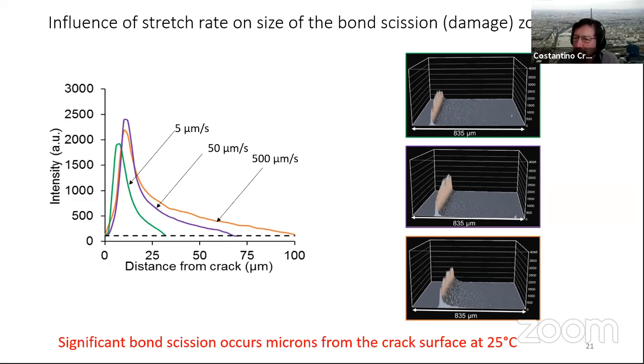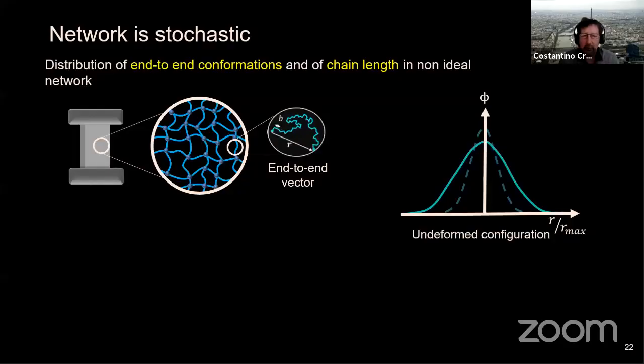These are very simple networks. They are very homogeneous. So they are just elastic chains connected together. So you could think that the breakage could be very close to the crack plane, as is normally used in models, and maybe not as far away from it. Now, the key reason why it's not the case is that in reality, although the stresses are well behaved in the continuum mechanics sense, in the molecular sense, the forces on molecules have a very wide distribution. The molecules between cross-linking points, first of all, have different lengths because the cross-linking is random, but you could also work with fixed length molecules. But the most important thing is the end-to-end vector of each molecule has a distribution.